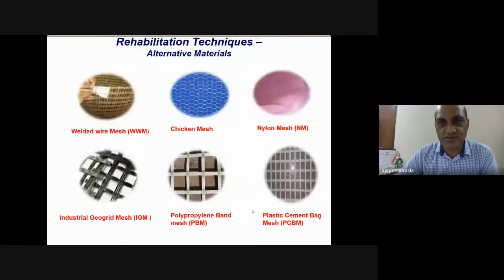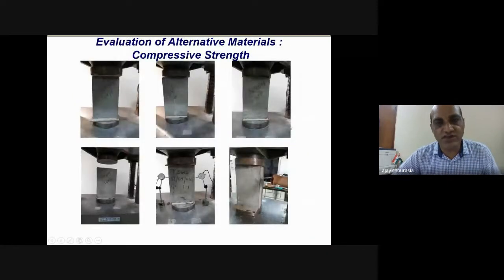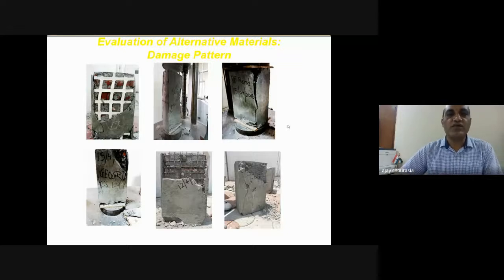And whatever the embracement or jacketing using all these different materials which was carried out on the unreinforced masonry prisms or wallets, have been then plastered, embedded within the plaster of 1:4 cement mortar, and it was subjected to uniaxial compressive loads to understand the compressive strength, stress strain behavior and damage pattern. The axial load was applied at the rate of 4 kilonewton per minute, very slow axial load, and this is the typical damage pattern which was noticed. Basically, the spalling of the plaster, separation of the plaster and the alternative jacketed material, and in a few cases the crushing of brick units also have been noticed.